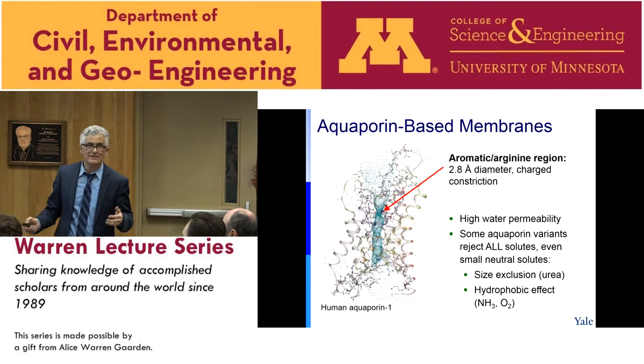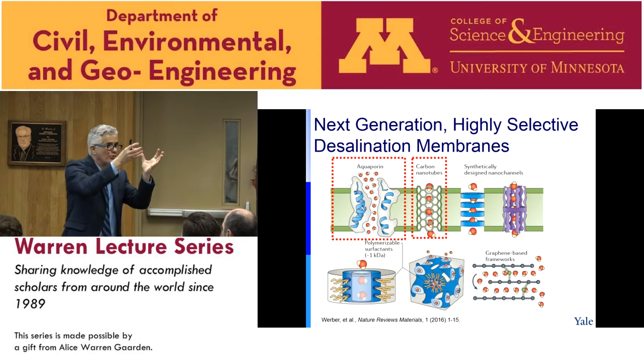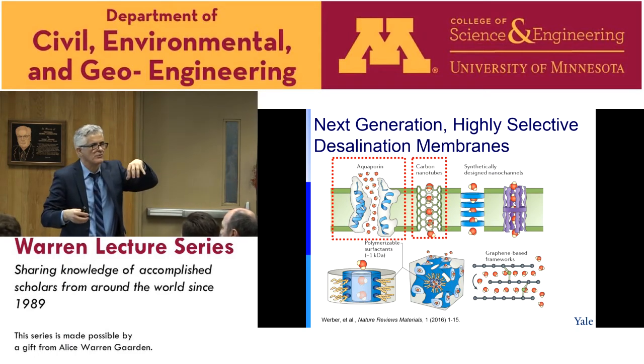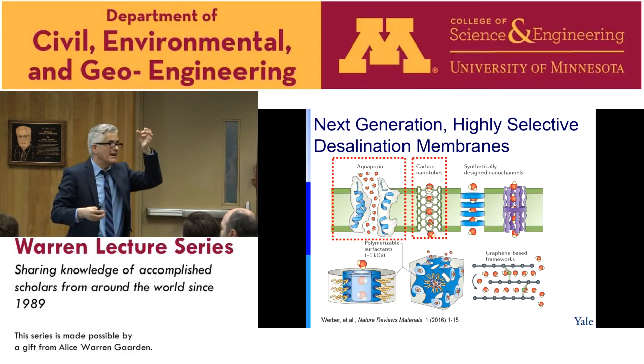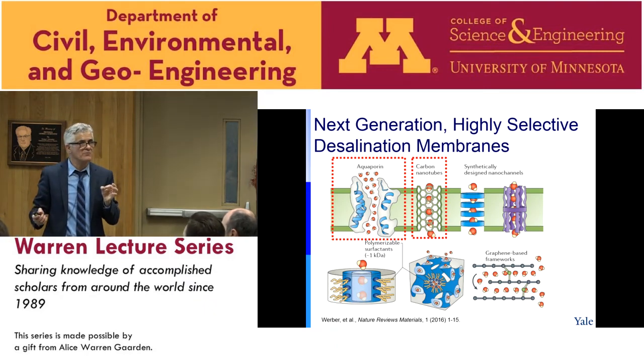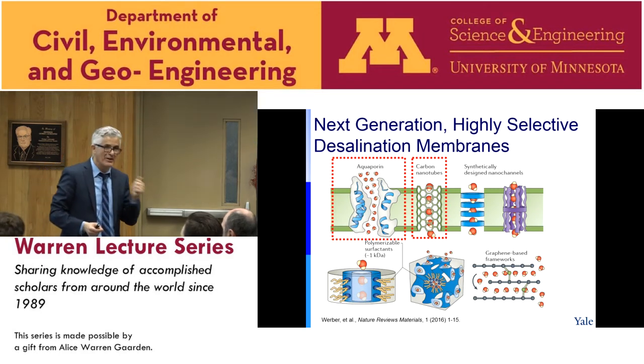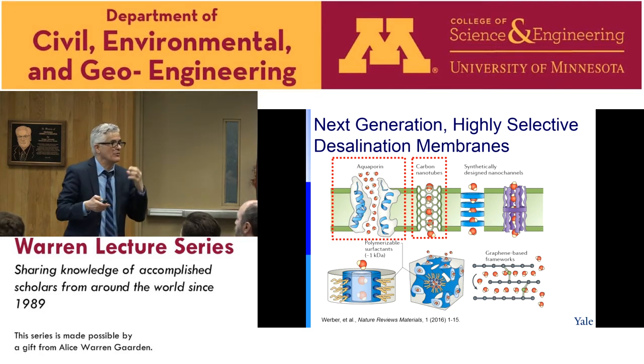What we are trying now is to take some liquid crystal surfactants and create the pores without incorporating any carbon nanotube, and have the pores as the channels for water permeation. We were able to get a pore up to 1 nanometer, but again, we show some ionic conductance, but water did not go through, and even gas did not go through. So whatever looks like 1 nanometer, probably it's not open enough, and we're trying to find some way to open it.